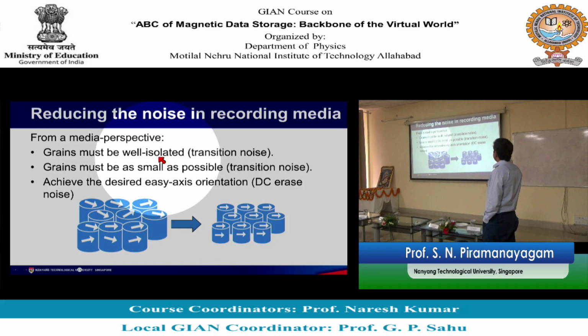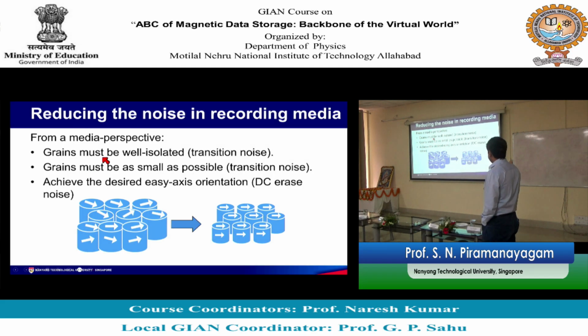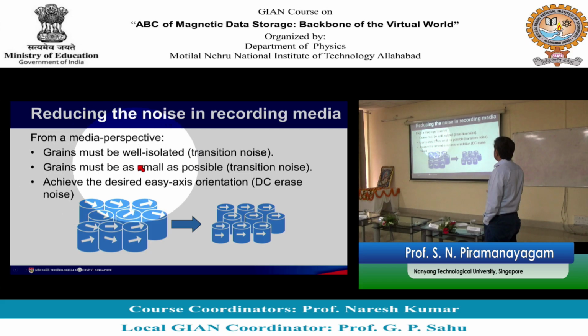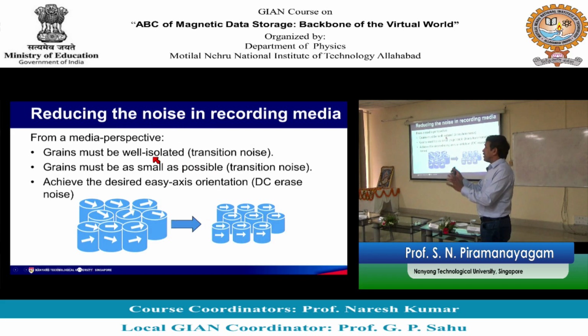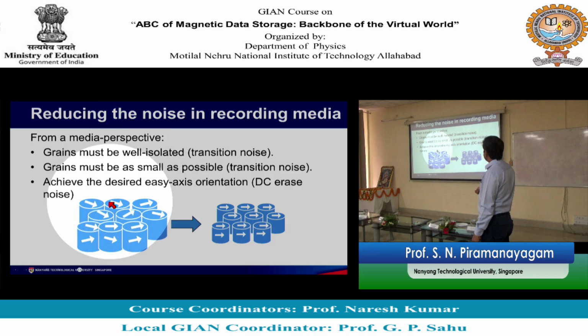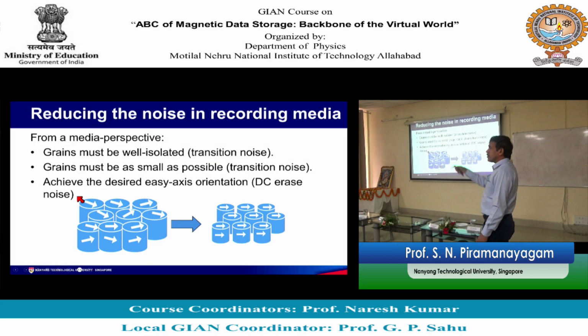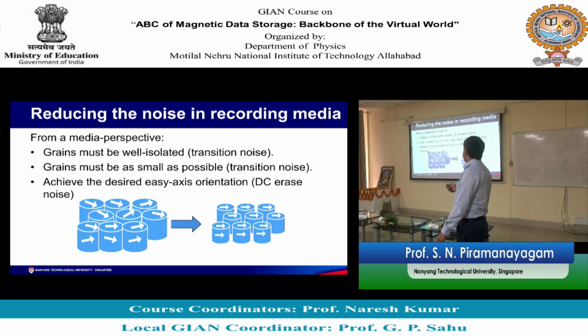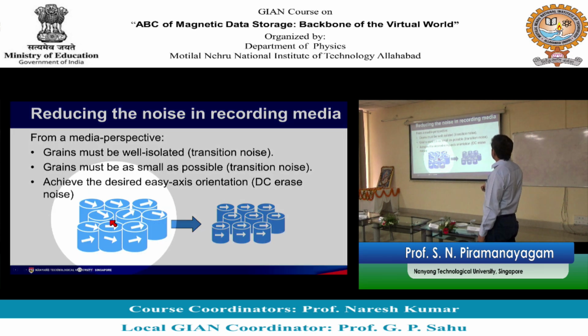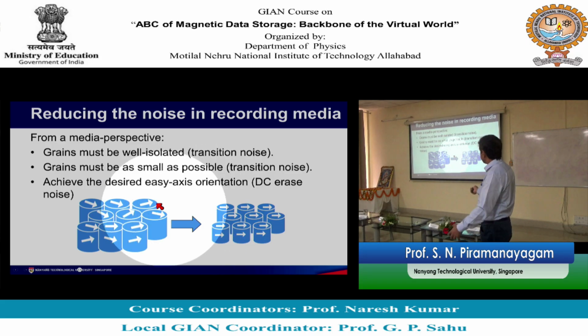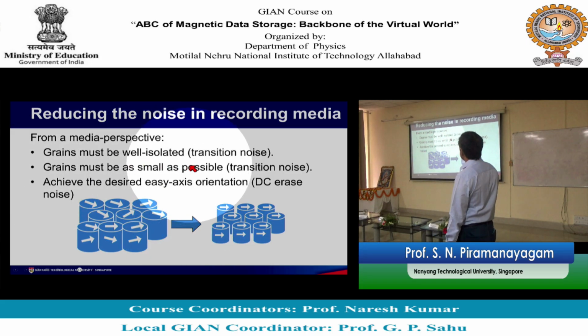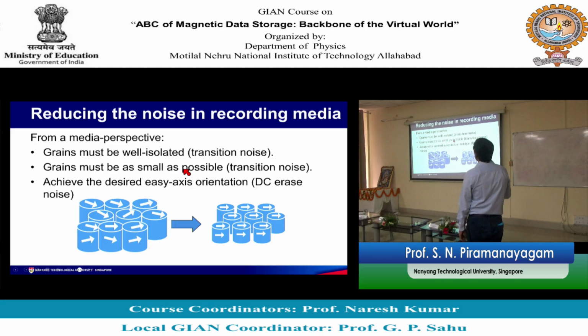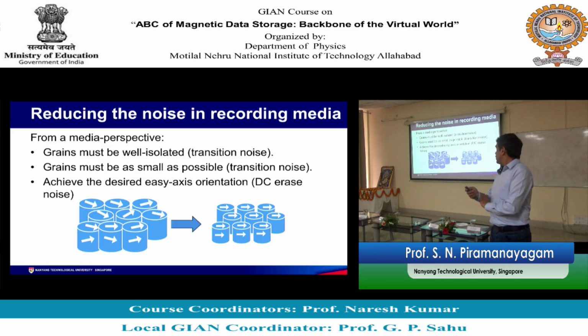We want to reduce the transition noise, so we must isolate the grains from each other, and we also want to make the grains as small as possible. If the grains are bigger and you try to write a bit somewhere here, the transition has to go through a very large region. The transition cannot happen through half of the grain, so it has to go through the grain boundary. If there are big grains, you will have a very big transition. If you have small grains, you will have a smaller transition. So grains also must be as small as possible. These are a few things that we learned yesterday.